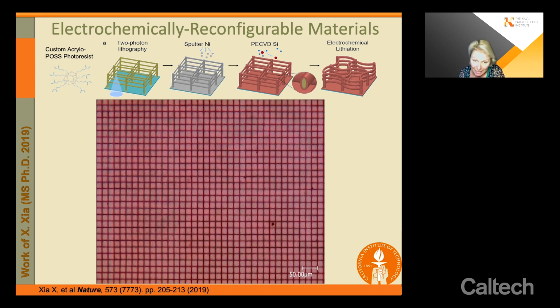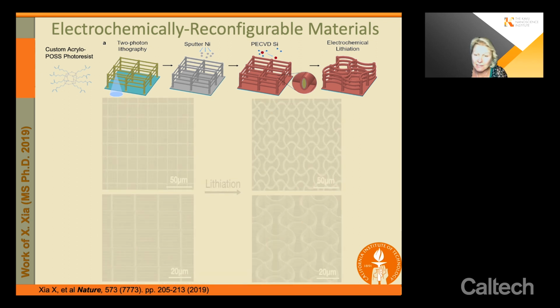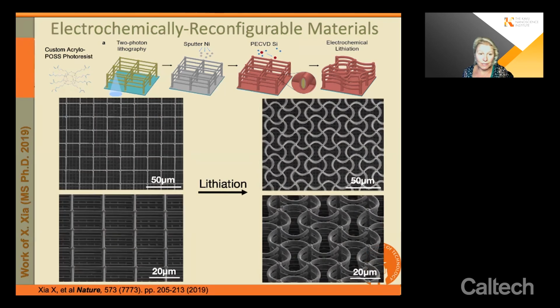And what you're looking at here is he's lithiating it. So this is a larger structure. And you can see that in response to lithiation, it's forming this very neat pattern. Now, I'm a musician, so to me, these look like violins, but to many of you, maybe they look like sinusoidal patterns. So here they are. I'm showing you these originally tetragonal straight beams as they're buckling into these curved sinusoidal type patterns. Now, this is its response to lithiation.